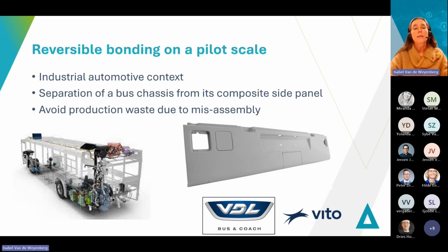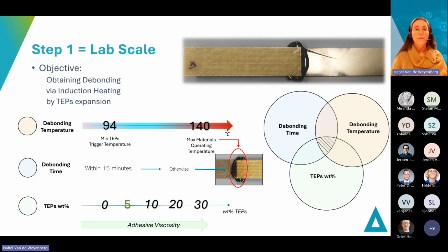In this particular example, we wanted to avoid production waste due to misassembly. You have huge panels that need to be bonded in a production process, and sometimes a misalignment occurs. If you want to debond your components, your composite panel gets quite often damaged. So this is something that we want to avoid by using this reversible bonding technology. First of all, from a technical point of view, of course, we start with a lab scale experiment, and we wanted to obtain debonding through induction heating, because the steel chassis is allowing us to use the induction heat in a very easy way.